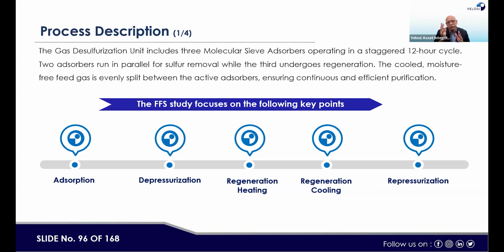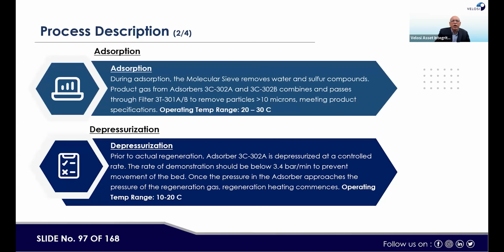So at that stage, the process shifts to train 2, or equipment B, adsorption tower B. Under that process, this first adsorption tower goes under depressurization, and then we have to regenerate the catalyst bed to be more active, and after regeneration, which is at high temperature, we have to repressurize the system again. In this way the system goes through cycles, and this cycle was being completed almost in 12 hours. In the adsorption process, the adsorption takes place between 20 to 30 degrees Celsius. Then depressurization also takes place between 10 to 20 degrees Celsius because the temperature drops when depressurization takes place.